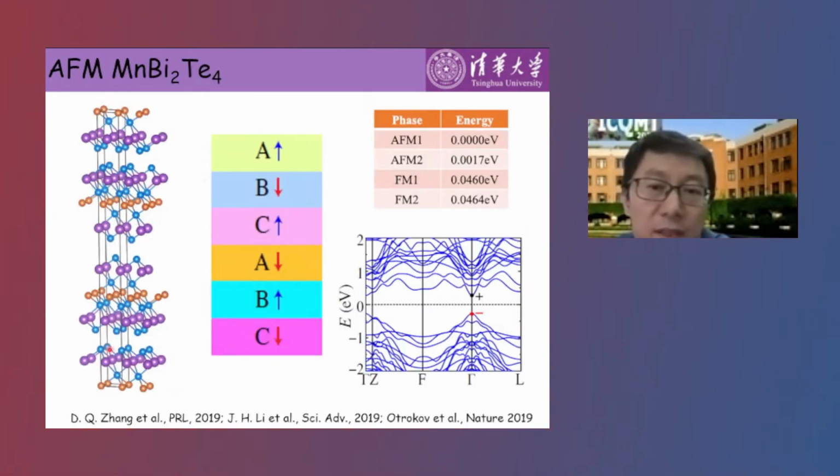In about 2018, the first intrinsic magnetic topological insulator, manganese bismuth telluride, was proposed and ignited intensive research interests. It exhibits a layered structure by stacking van der Waals' septuple layers of manganese bismuth telluride. Each septuple layer can be viewed as an extra manganese telluride layer sandwiched at the middle of the well-known bismuth telluride quintuple layer. It enters an antiferromagnetic ordered state below 25 Kelvin.